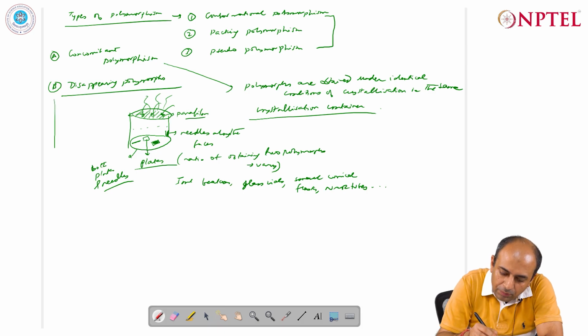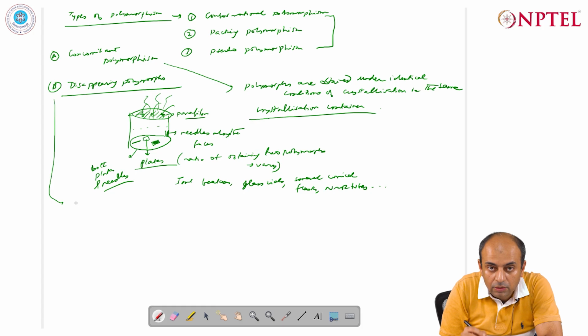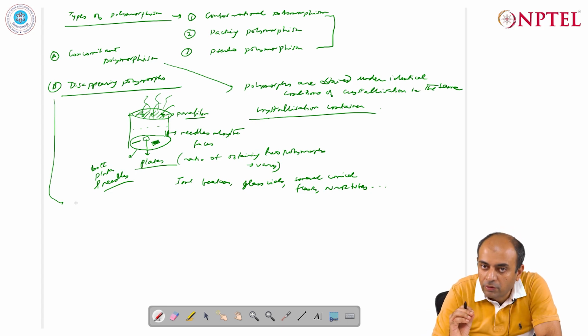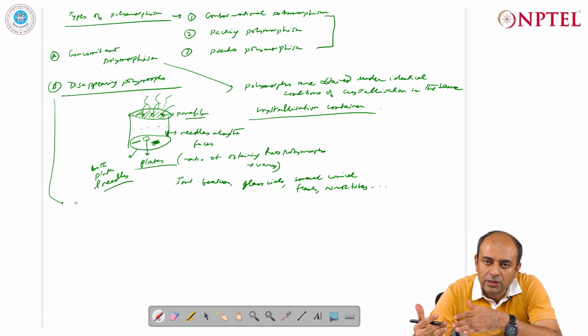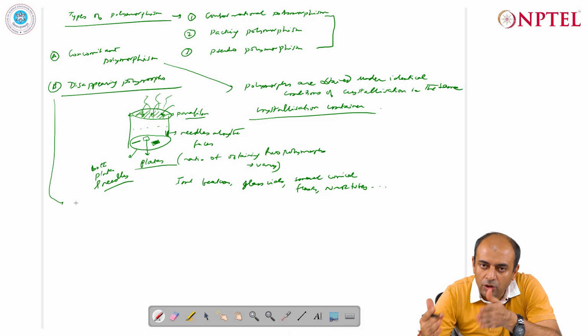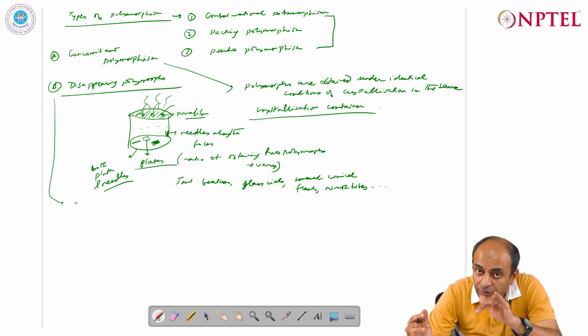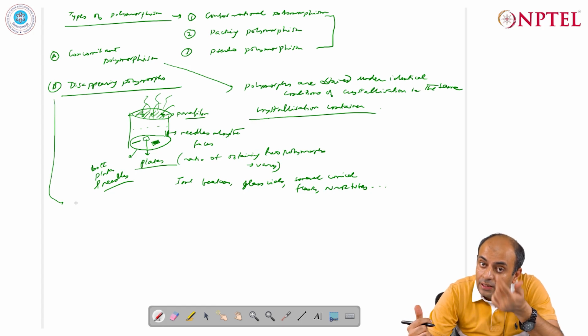Then comes a very important phenomenon, disappearing polymorphs, where say you have crystallized a particular compound and got one particular polymorph. Now the next time whenever you try to crystallize that compound, the initially obtained polymorph does not crystallize. You always get a new polymorph, no matter what you do. You change the conditions of crystallization, you screen it very extensively using different methods. Say you take polar solvents, or polar non-polar solvent combinations, or non-polar solvents, you change the temperature, you change the crystallization containers. Sometimes you even change the laboratory where you are trying to crystallize that compound, so that you do not have any possible contamination in the air which can interfere with the formation of the initially obtained form.